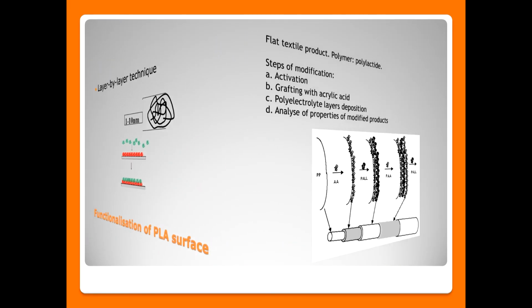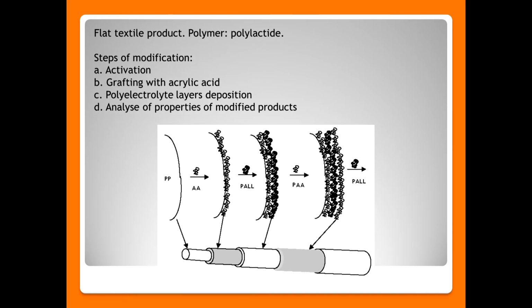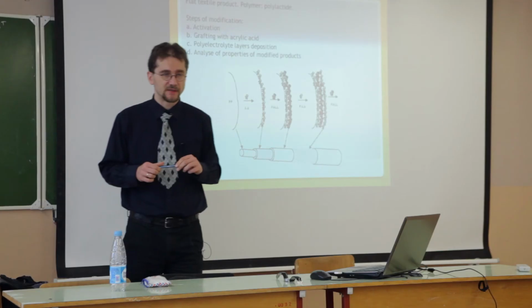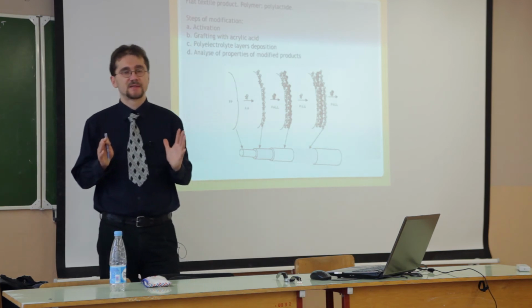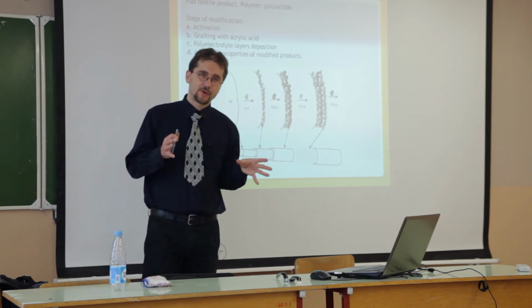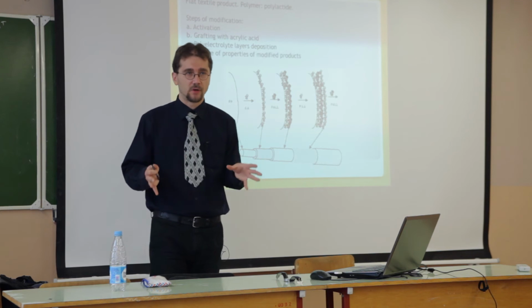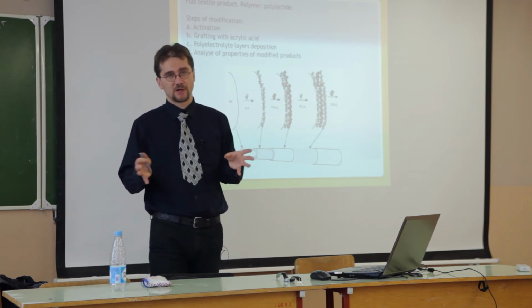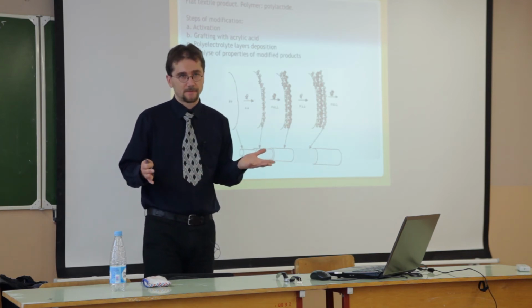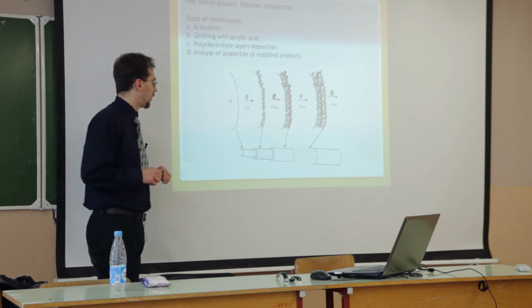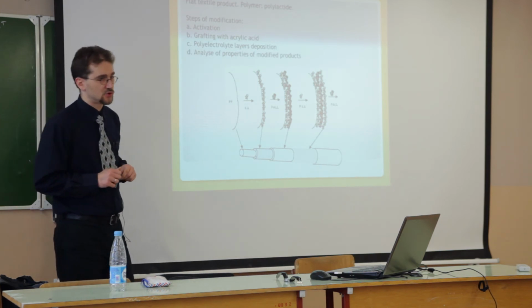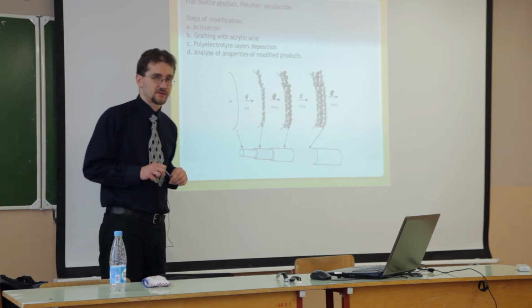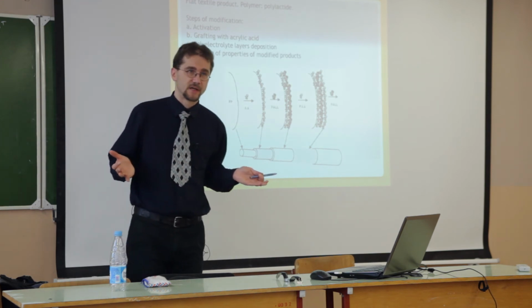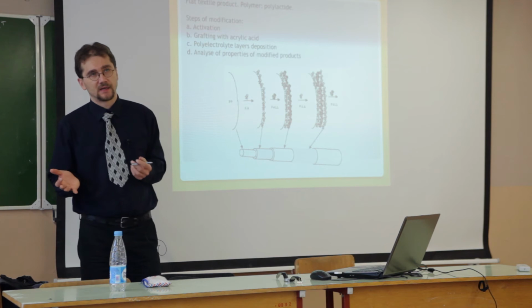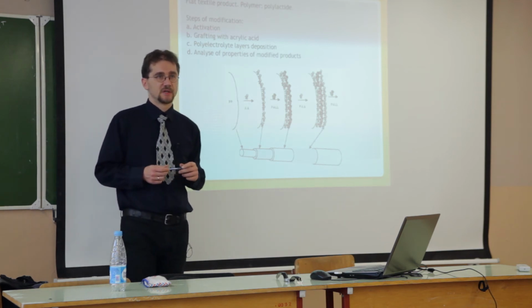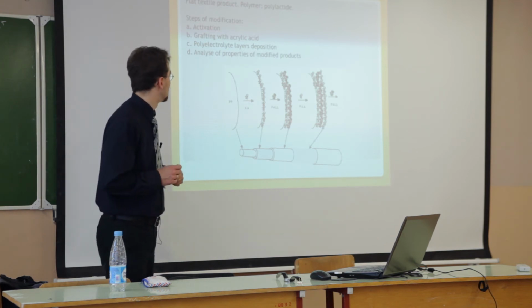But always the main problem with the application of the layer-by-layer technique is that all chemicals must be electrolytes or polyelectrolytes. So all layers must be charged, plus or minus, and of course the modification material should also be charged. It is difficult because we do not have textiles or polymers which are polyelectrolytes.